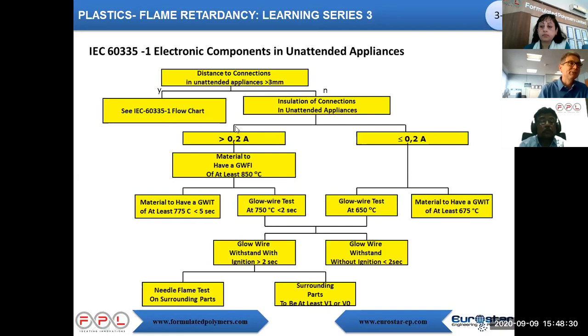Does my material carry more than 0.2 amperes? Yes or no? If it's above 0.2 ampere, then no way, you have to survive glow wire flammability index at 850 and pass a test on part at 750. And then you are there. If the material is below 0.2 amperes, it's an easier test, you have to comply with 650 glow wire, or you have a GWIT of 675. In case of below 0.2 amperes, it's quite simple.